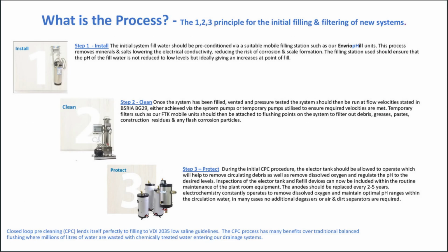So what is the process? Again, we're following the 1, 2, 3 process. So install. The initial system fill water should be preconditioned by a suitable mobile filling station, such as our EnviroFill units. The process removes minerals and salts, lowering the electrical conductivity, reducing the risk of corrosion and scale formation. The filling station should be used to ensure the pH of the fill water is not reduced to low levels, but ideally giving an increase at point of fill.